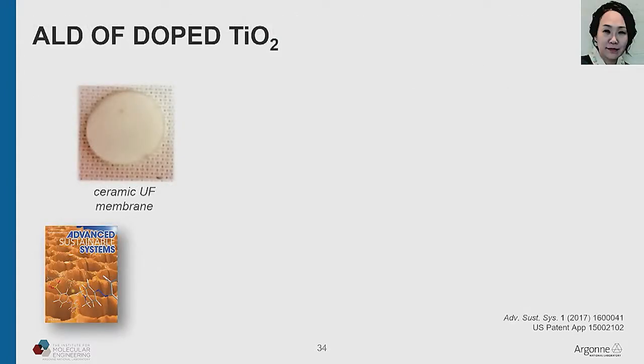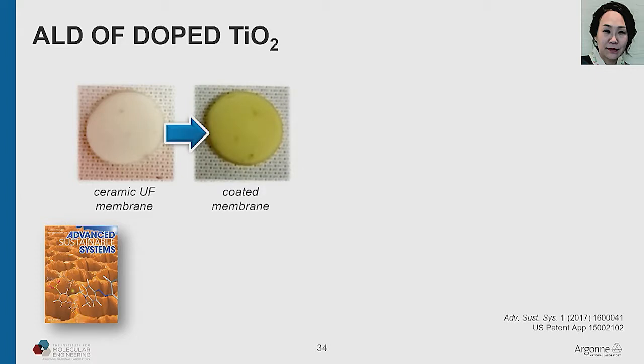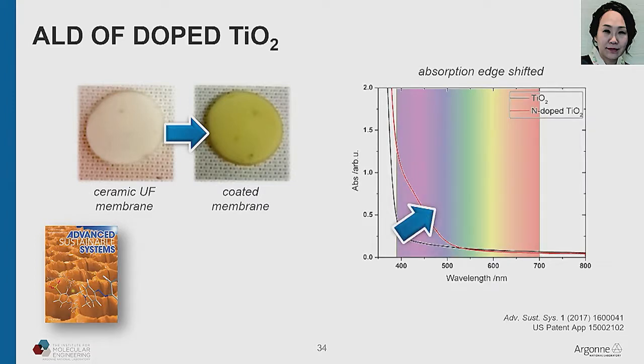And you can do that with titanium dioxide by doping it. And so in this case, we've got here an ultrafiltration membrane. This one is ceramic. And we're going to coat that with atomic layer deposition. Now, I didn't say it explicitly, but one of the nice things about ALD is that it's conformal even for non-line of sight deposition. So even a tortuous thing like a membrane, those precursors will find their way through. And you can decorate the entire membrane with a coating this way. And because you're just doing an atomic layer at a time, you're not clogging up the pores unless you do many, many cycles. And you can see by eye that this thing absorbs visible light when you coat it with doped titanium dioxide. You don't need a spectrometer. Obviously, the color has changed. Here's the spectroscopy if you want to see it. So before, if you just use normal titanium dioxide, it only picks up absorption when you get into the ultraviolet regime. But now we're grabbing the violet into the blue region with this nitrogen doping.